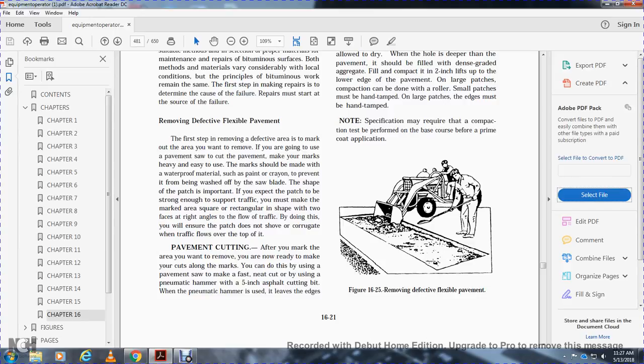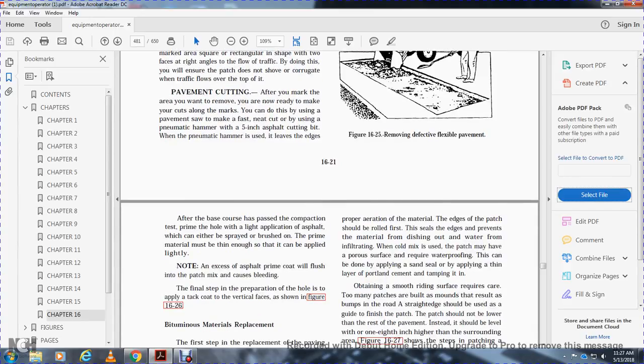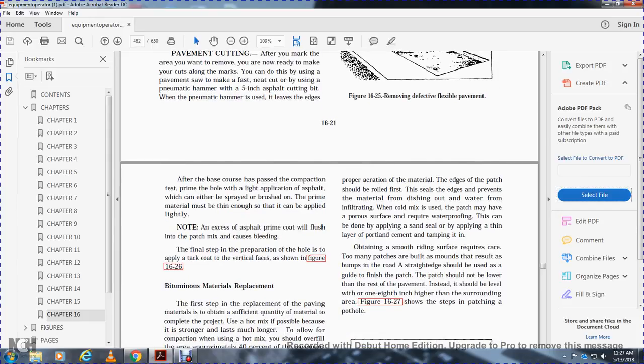Figure 16-25 shows removing defective flexible pavement. After the base course has been compacted, prime the hole with a light application of asphalt that can be either sprayed or brushed on. The prime material should be applied lightly. Note: excessive asphalt prime coat will flush into the patch mix, causing bleeding. The final step of hole preparation is to apply the tack coat on the vertical faces, as shown in Figure 16-26.